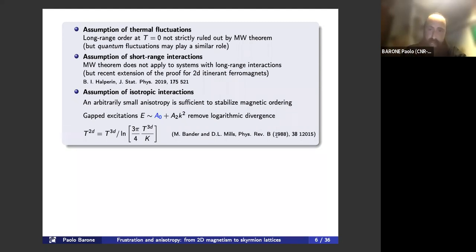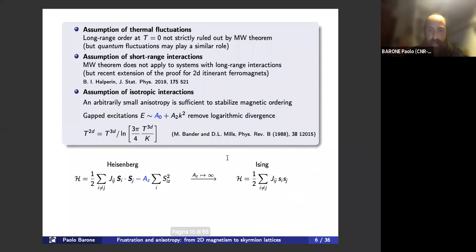And this was, for instance, realized by Bander and Mills in the late 80s when discussing exactly the thin ferromagnetic films, where they show that indeed the long range ferromagnetic order could be allowed in the presence of an arbitrarily small uniaxial anisotropy. But of course, then the critical temperature was importantly renormalized in the 2-dimensional limit. Of course, this also allowed to reconcile the Heisenberg and the Ising picture.